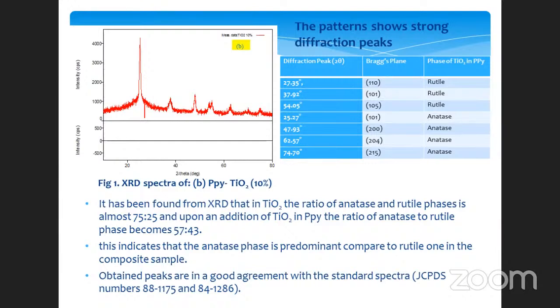So a conclusion can be drawn that it has been found from XRD data of the TiO2 that the ratio of anatase and rutile phases is almost 75 to 25 for the pure TiO2. But when it is added into the polypyrrole matrix, it becomes 57 to 43. And this indicates that the anatase phase is predominant in this composite.